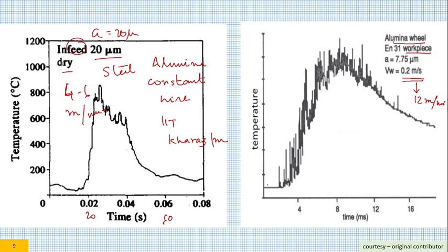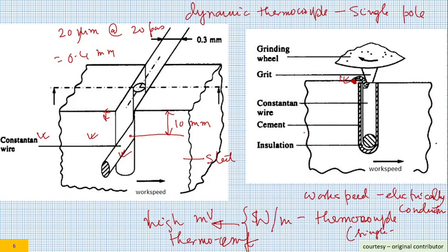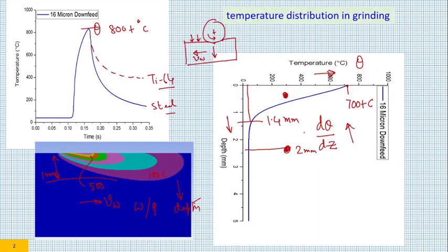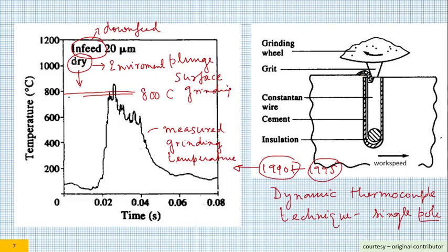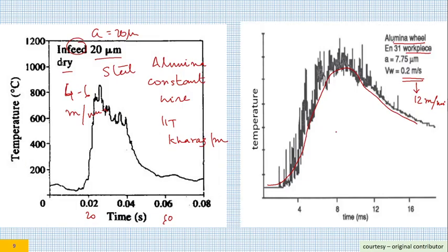This was done at a much later stage, and you have a nice profile of measured temperature like this, which by the way matches very nicely with the temperature profile that I have shown. These are computed profiles. This particular profile is a computed profile. So this computed profile matches nicely with the actual measured temperature that is shown here, as well as here. This is not coming from IIT Kharagpur, this is coming from somewhere else. Because of shortage of time, I could not identify all of them.